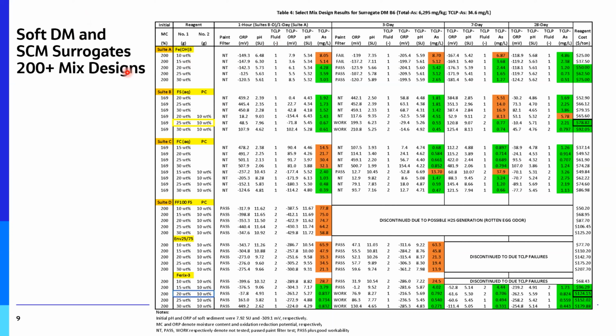Because the key is up here, and what you see is we have our moisture contents that we're tracking in the leftmost column. We have our reagents, again, limited to 2, and our priority was to be adding iron into the system, and then if we needed solidification, to begin adding things like Portland cement. And then we track the paint filter, ORP or Eh, pH, the TCLP fluid we were using, the ORP during TCLP, the TCLP pH, because that's the regulatory criteria, or one of them at any rate, the TCLP arsenic, right? And so green means you passed, red means you failed, and we needed to track that.